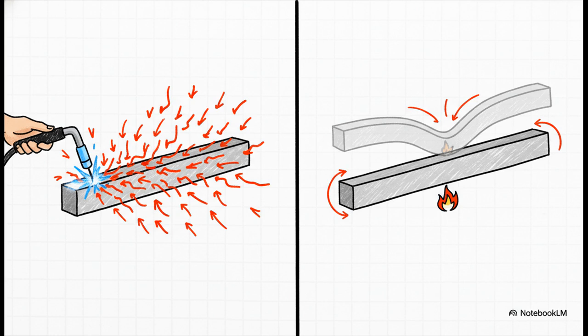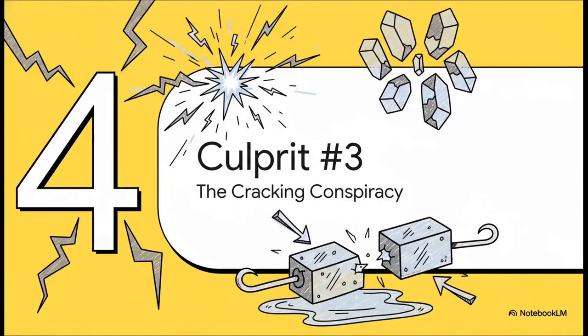It's a constant fight to keep the heat where you want it and to stop the metal from turning into a pretzel. Right, so let's say you've punched through the oxide layer and you've managed all that heat. You're not done yet. Now you have to worry about what happens when that puddle of molten aluminum starts to cool down. Because this is where the metal basically conspires to tear itself apart.